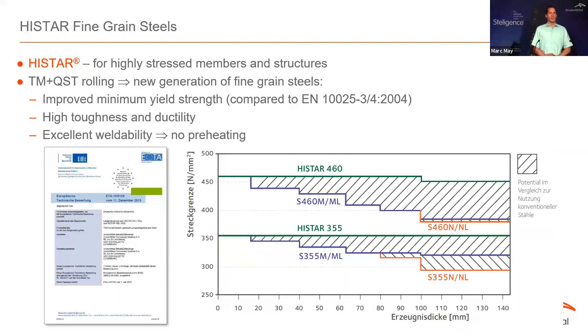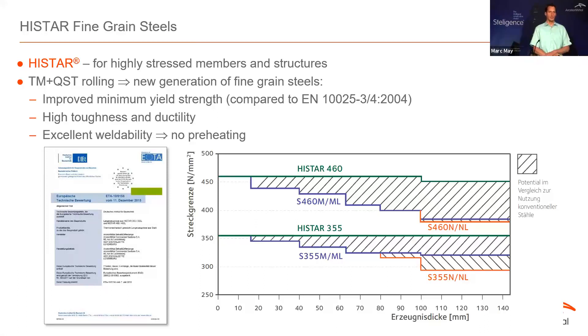This process is covered by an ETA — European Technical Assessment — and we sell this steel under the trademark Histar. Histar has higher strength than standard steel in EN 10025. Here you see the yield strength reduction steps required when using EN 10025 steel (in blue) or part 3 (in red). With Histar 355, there is no reduction in yield strength across the whole thickness range — you can use Histar 355 at 140 mm with 355 MPa yield strength. For Histar 460, there is one reduction step at 100 mm from 460 to 450 MPa, giving a big advantage for economical structures using heavy sections.